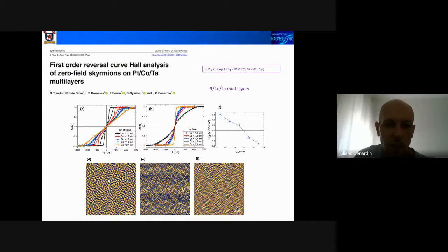And you can see here that the E sample, the 1.7, has smaller stripe domains and several isolated domains that could be skyrmions, that are very small. And in the other samples, you don't see this. This is in the demagnetized state.